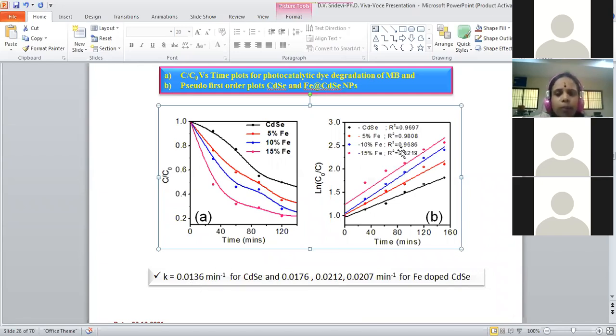For CdSe, it can be determined from 2.303 times the slope, sir. Here also there is no definite relationship between the rate constant and the dopant concentration. See, 0.0136 for CdSe, 0.0176 for 5%, then 0.0212 for 10%, and 0.0207 for 15%. There is a decrease in rate constant.